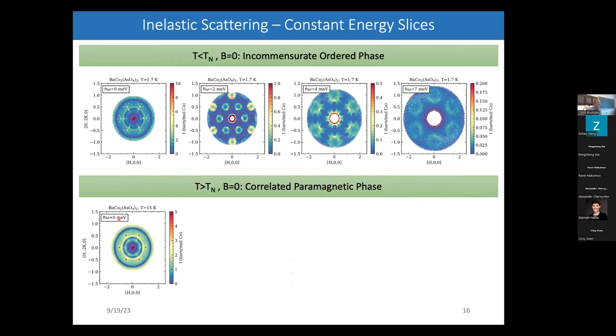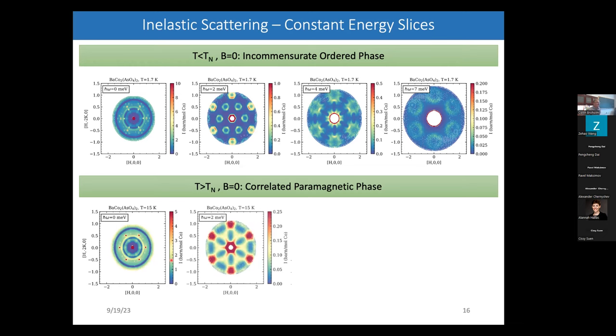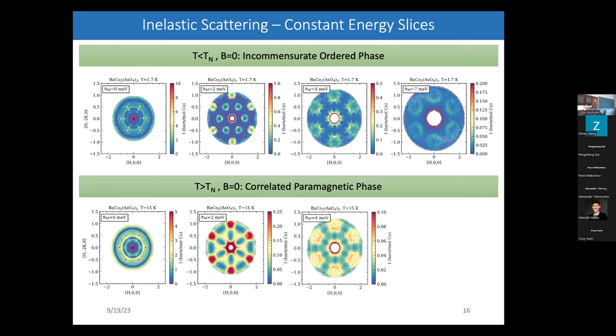So at low fields and at elastic scattering, I now no longer have these satellite peaks. But then when I come up towards higher energy transfer, now I'm in a paramagnetic state. Then I see these kind of filled in the rings, if you will, but I still have this kind of blob of intensity. And then as I come up in energy transfer to 4 millielectron volts, now it's actually not that easy to distinguish these from each other.